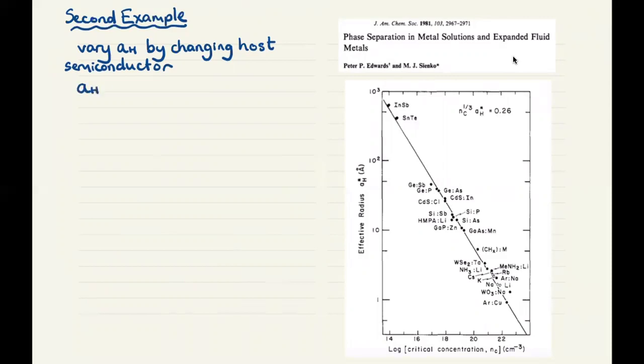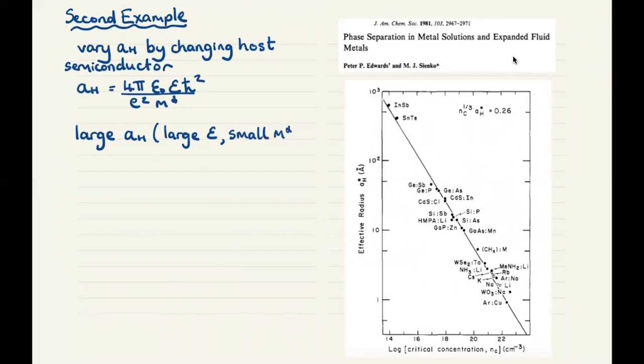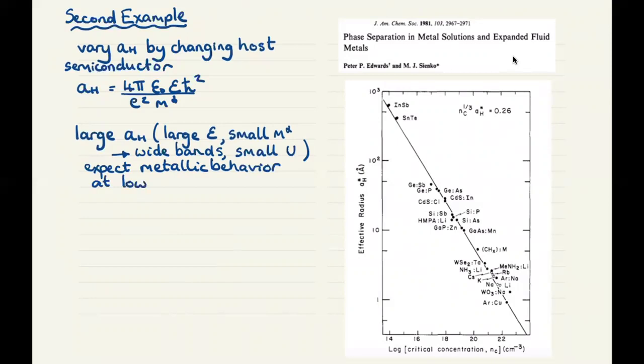And remember again, the hydrogenic radius is 4 pi epsilon 0 epsilon of the host semiconductor, h bar squared over e squared m star. And so when we have a large hydrogenic radius, corresponding to a large dielectric constant and a small effective mass, this means that we have wide bands, with a very covalently bonded semiconductor and a small U. So when we have a large hydrogenic radius, we expect metallic behavior at lower dopant concentration.